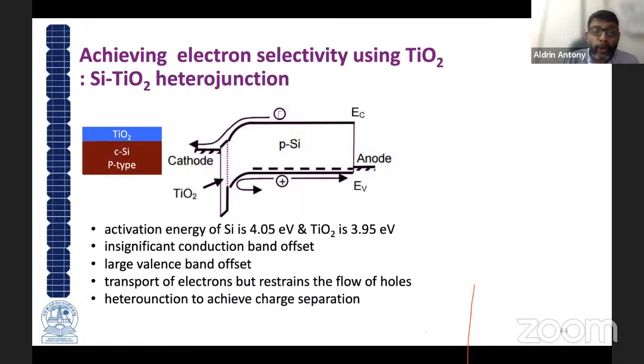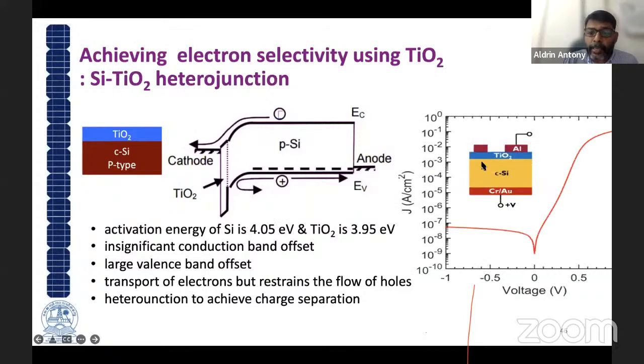And like I told you, titanium dioxide forms a very good band alignment with the crystalline silicon. So it can allow the electrons to move, and it can block the holes from moving in this direction. We tried this by depositing titanium dioxide of 3 to 4 nanometer by atomic layer deposition. Then we fabricated a device just like a diode, biased this diode and took the dark characteristics of the diode.